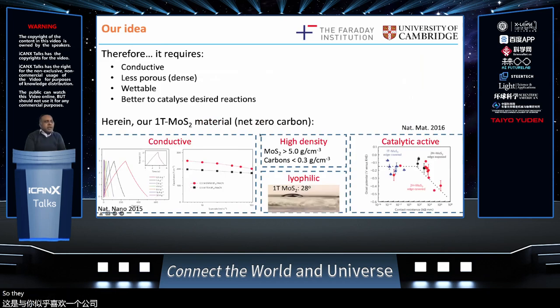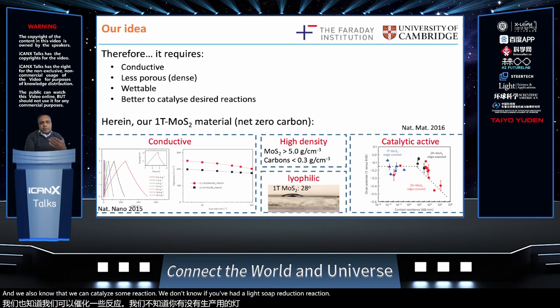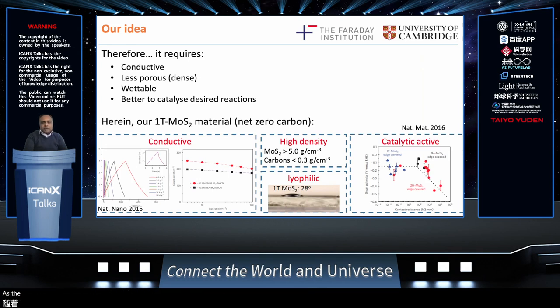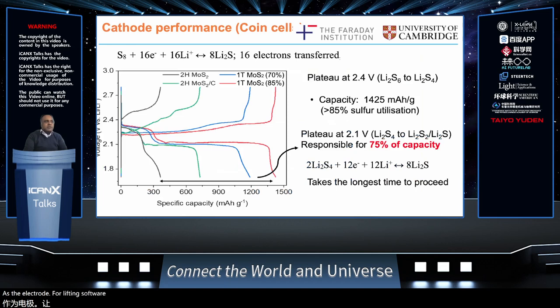So as I said, when we looked at the basic properties of the metallic 1T phase MoS2, we know that it's highly conducting. We know that it has low surface area. We know that it's highly lyophilic. And we also know that it can catalyze some reactions. We don't know if it'll catalyze a sulfur reduction reaction, but we know that it has some catalytic activity. So we decided to implement the 1T phase MoS2 as the electrode for lithium sulfur batteries.